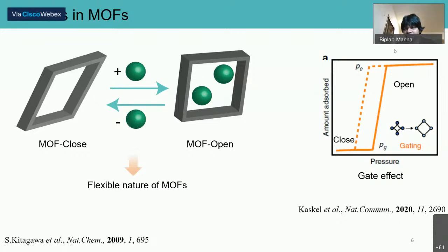And here you see the structural opening, which we can call a gate effect. When the phase is closed, there is no adsorption of the guest molecule, and suddenly at a particular pressure, the guest molecules come in at a time and open the structure. It is called the gate opening pressure. With this flexible nature of MOFs, there are a lot of nice inventions, or you can call them discoveries, as well.